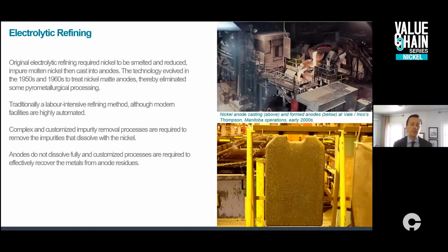So this is just a little bit more context as to what these electrodes look like. The photo on the top right is actually a photo of the smelter that we operated in Manitoba from the early 1960s until a few years ago. And what it's showing is pouring molten nickel matte that's about 75% pure into a mold. And after several days, that molten nickel matte has cooled and solidified into a nickel anode, which you can actually see in the bottom photo on the right. And so that's what goes into a plating bath as an anode, dissolves slowly, and is used to plate a nickel cathode.